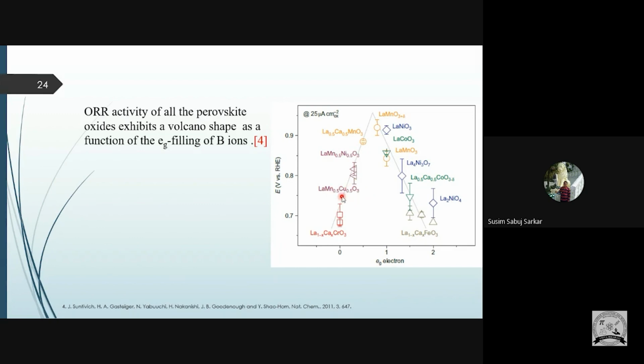If we replace Cu with Ni, in the case of Ni that means t2g6 Eg2, so in Eg two single electrons are there, not paired. And in the case of Mn also, t2g3 Eg2 or t2g3 Eg1, that's why the activity increases toward that. In the case of LaMnO3, Mn3 plus is again t2g3 Eg1, that is the highest activity. Again it drops if we increase the amount of Eg electrons.